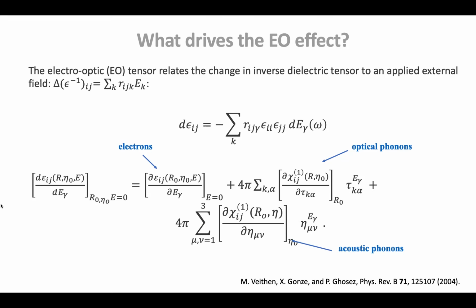But in materials like barium titanate or lithium niobate, they're piezoelectric. And so if you apply electric field, you have converse piezoelectricity. It changes the lattice constant. That changes the band structure. That changes Chi1, right? And so they're actually different frequency regimes. At low frequency, all of them play out. At high frequency, only electronic Chi2 works. In intermediate, you have both kinds of phonons, and so you can see how the effect changes.